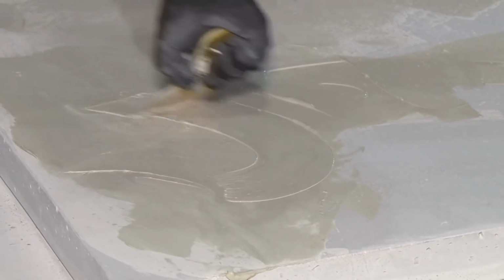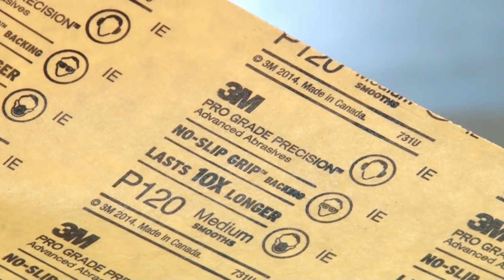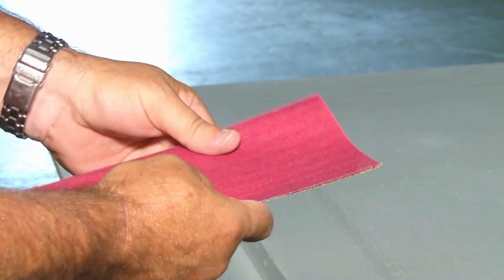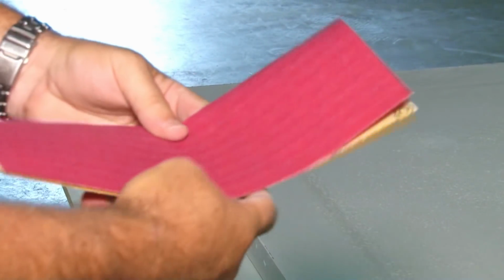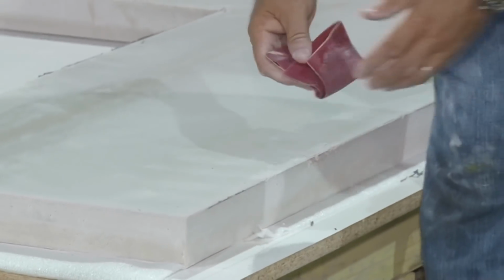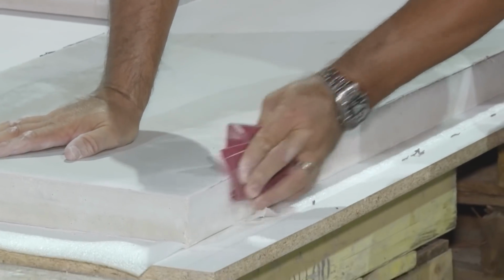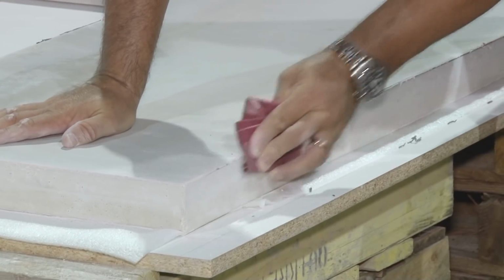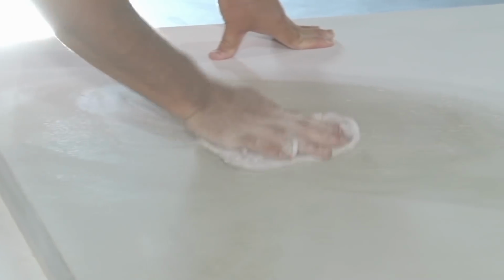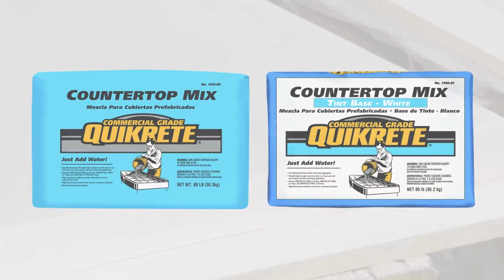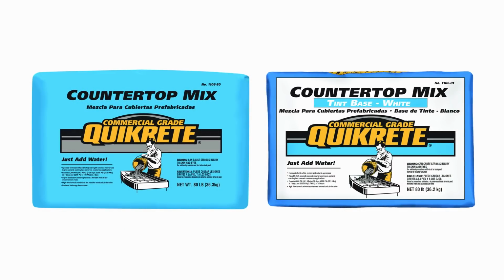Allow the Polyblend grout to dry. Then use a fine sandpaper to sand the surface, edges, and sides of the countertop. Once the surface is complete, cover the countertops again with plastic. Be careful not to allow the plastic to come in contact with the countertop surface. This could cause discoloration. QUIKRETE Countertop Mix will reach a compressive strength of 2,000 psi in 24 hours and about 3,000 psi in 3 days.